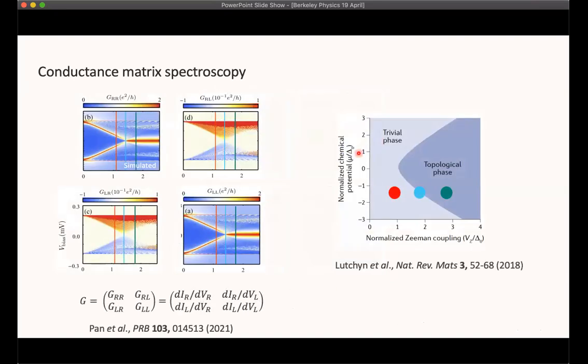So to go back to our attempt to map a topological phase transition as we go from the trivial to the topological phase, what we propose to do is to actually map the entire conductance matrix of these wires. And in doing so, observe that we can convince ourselves that we've entered the topological phase if we see two things. If we see a closing of the bulk gap at the phase transition, and we'll really convince ourselves that we've seen that closing if we see it in this non-local full wire length spectroscopy. And then we need to see in the topological phase the presence of these zero bias peaks on both sides of the wire, because there can be other effects that lead to additional conductance at zero bias, but there's stronger evidence for the presence of Majorana quasiparticles if they simultaneously occur on both sides.